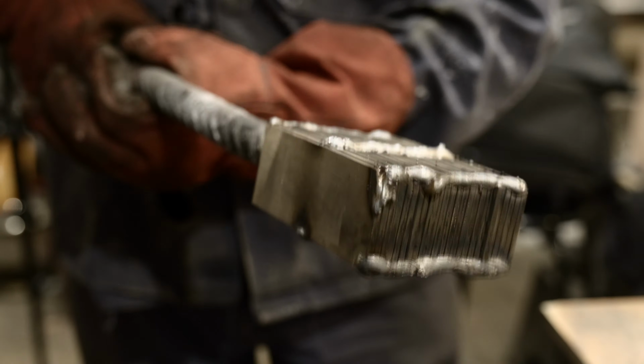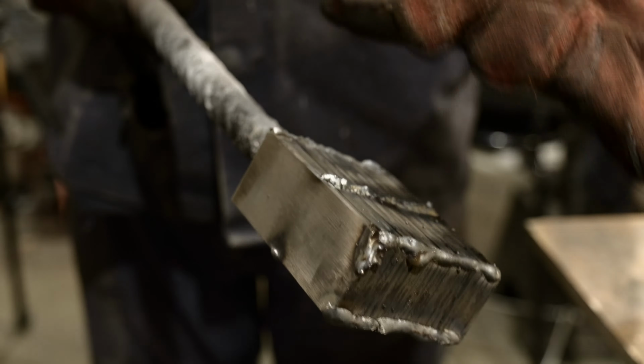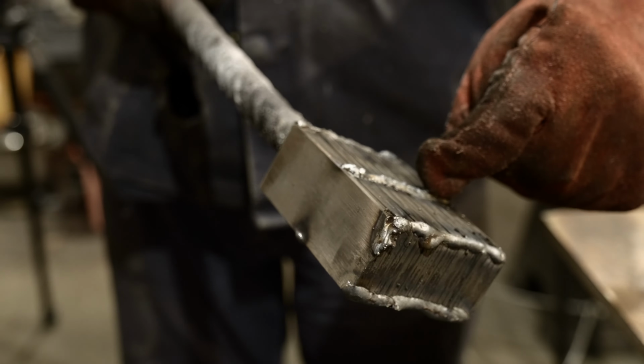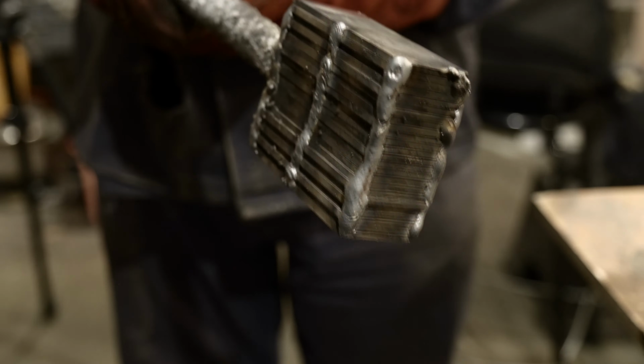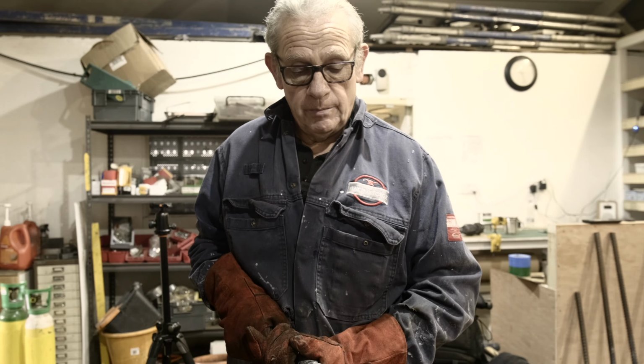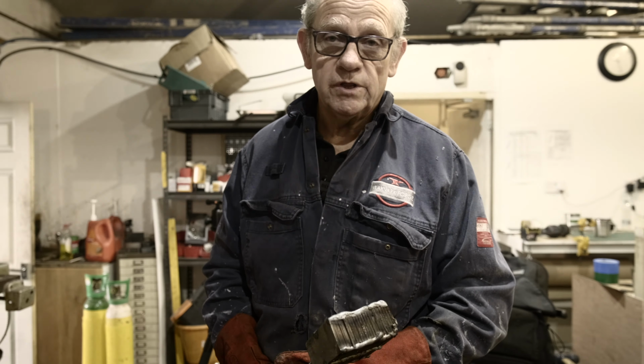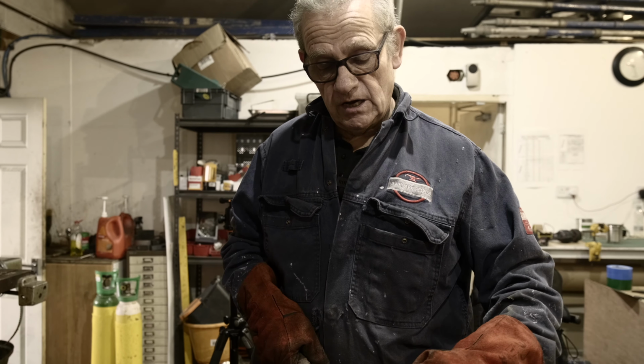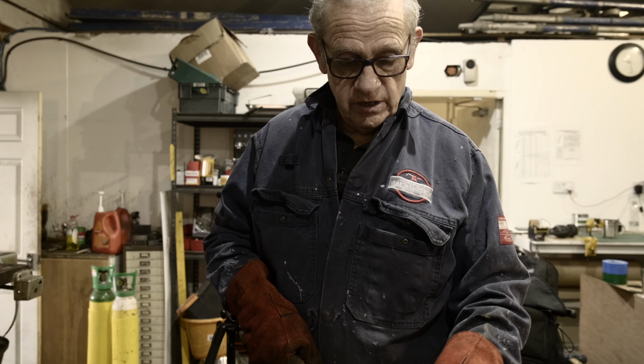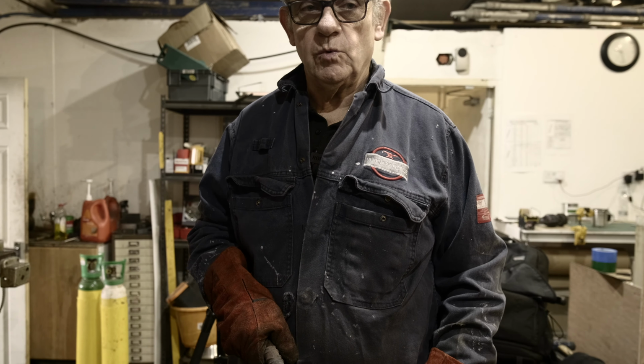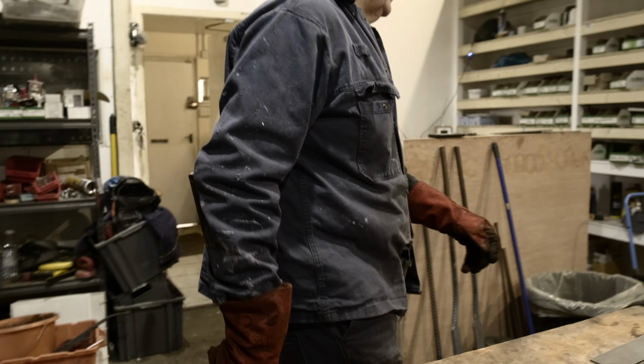Because my welding is rather bad, we've got a little bit too much. What we don't want to do is forge that weld into the actual material, otherwise it will show up as a white band, and we don't want that in there. But we just need enough weld on there to hold these layers together so they don't spring apart while we're going through the basic welding process. So we just go through to one of the grinders.